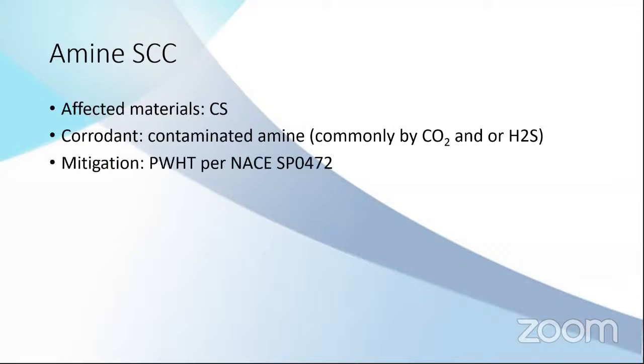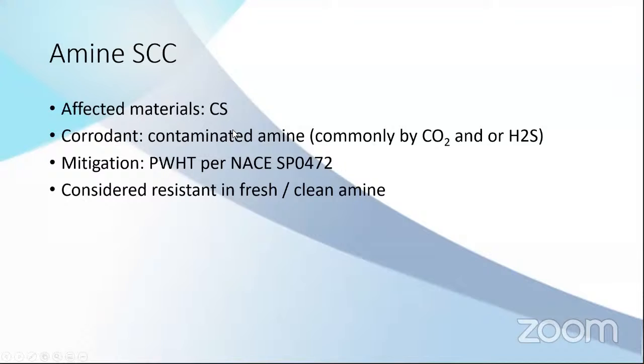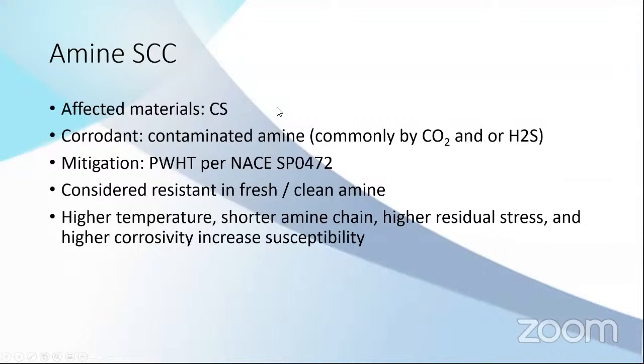The mitigation is simple. It's just post-weld heat treatment. And normally we refer to NACE SP0472. In this standard, there is already an explanation about how high the temperatures should be for the post-weld heat treatment. And just to make sure, fresh amine is not susceptible. It's resistant to amine stress corrosion cracking, only contaminated amine is a problem.